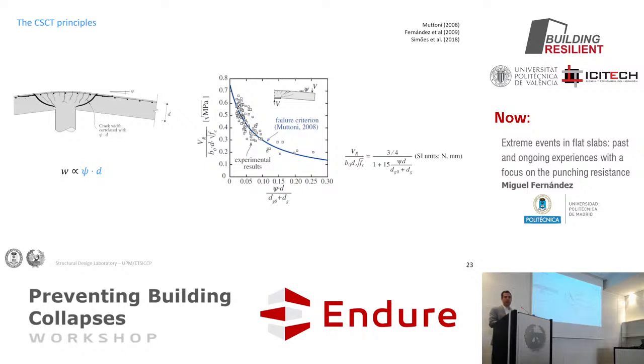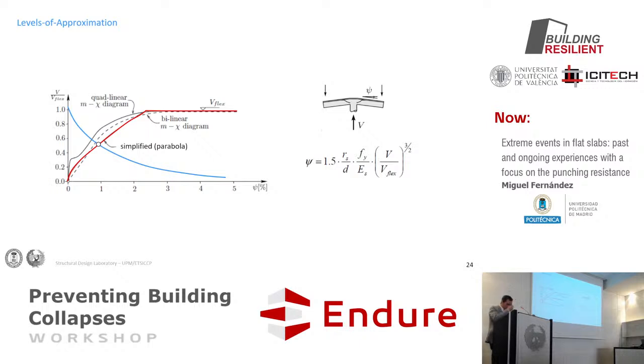I think it's a clear demonstration again that the key parameter is this opening of the cracks, and it's very consistent with the theory. And also another advantage, because we have been focusing on this failure criterion, is what happens with the load-rotation relationship. This is a very, very interesting point also, because as the theory is mechanically consistent, so it's based on a model with all its limitations, of course, you can refine the different parameters gradually, step by step.